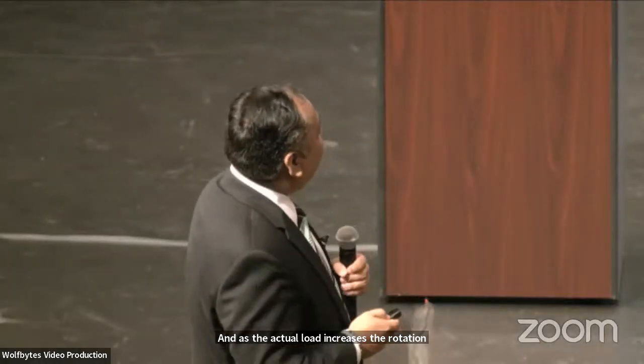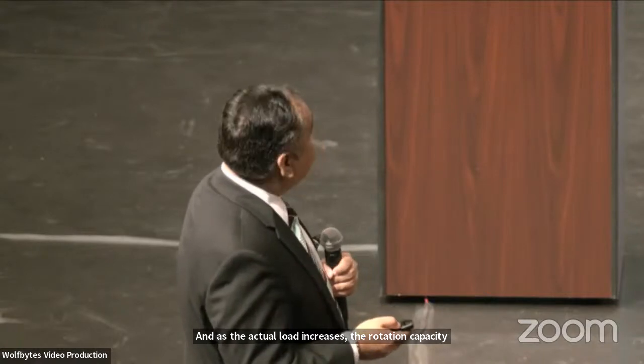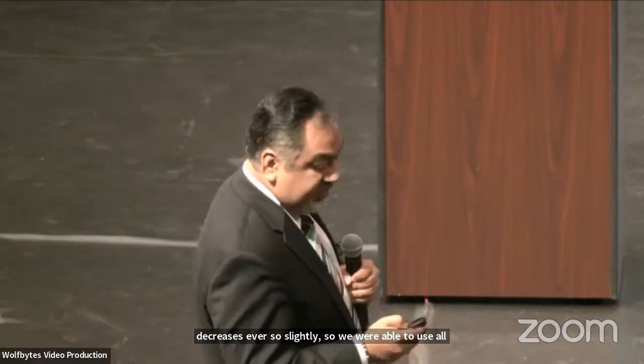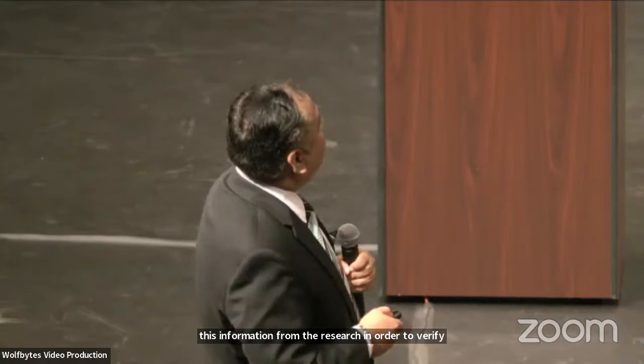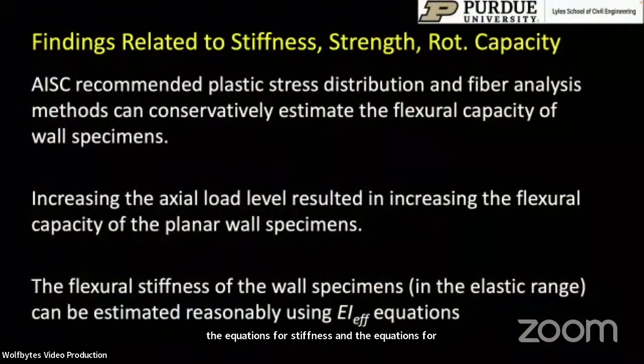So we were able to use all this information from the research in order to verify the equations for stiffness and the equations for strength. So AISC now recommends the plastic stress distribution and also permits the use of fiber analysis to estimate the in-plane flexural strength of the wall specimens.